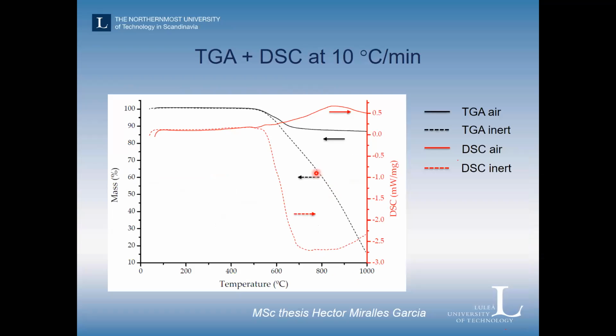The influence of air versus inert environment in nitrogen is illustrated here, and it could be looked at the black curves primarily. If we look at the black curve, the upper one is for when we do the TGA measurement in air, where there's a lot of oxygen that can interact with the resin. But when we have an inert environment, or semi-inert at least, the nitrogen,